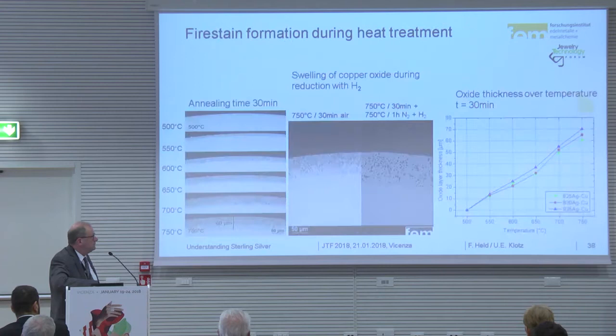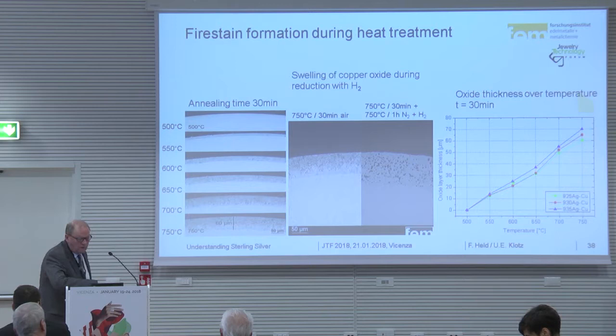This is the fire stain formation during heat treatment. We use an annealing time of 30 minutes in this line, and we use different temperatures. It goes from 500 to 750 degrees, and the annealing was done under argon and we take the specimens out. No, annealing was done under air here. And so we see the oxidation goes very fast. If we make a half hour annealing at 750 degrees, we have here 60 microns.